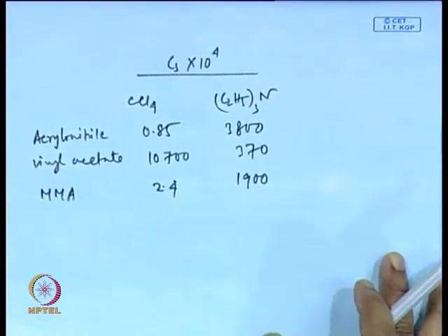So, what is the utility of transfer reaction, or what can it help you with in this learning on transfer reaction? Say you are trying to polymerize a monomer and at the end you are not able to get the high enough molecular weight which you planned from your experiment, then what are the possibilities? If it does not build molecular weight, and you know from the monomer structure that it is polymerizable by, say, radical polymerization route, then there could be transfer reactions happening. It could be happening with monomer, initiator or solvent, or there could be impurities present in the reaction medium.